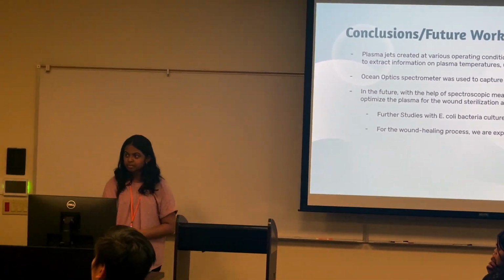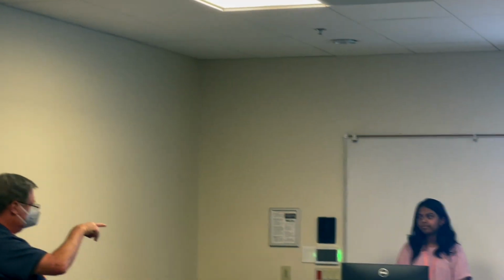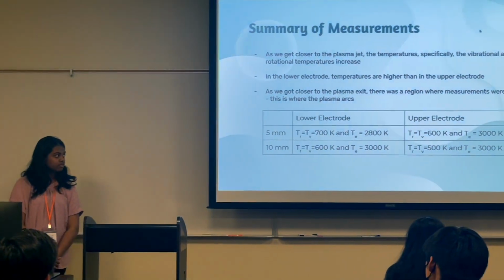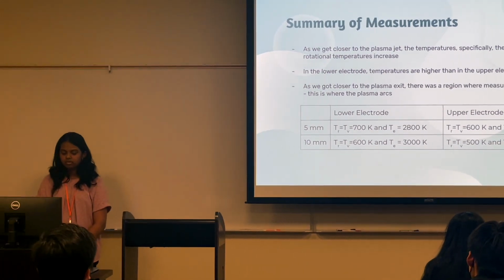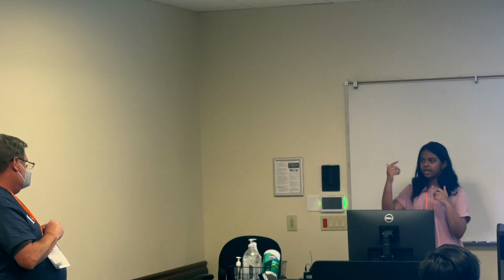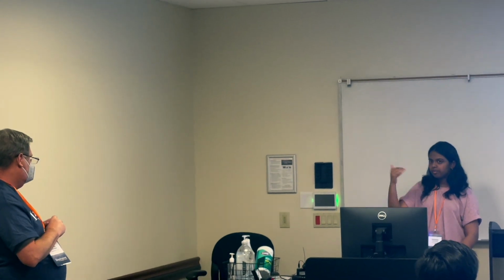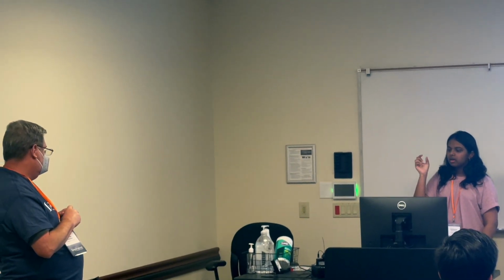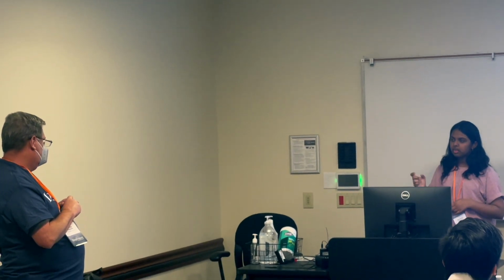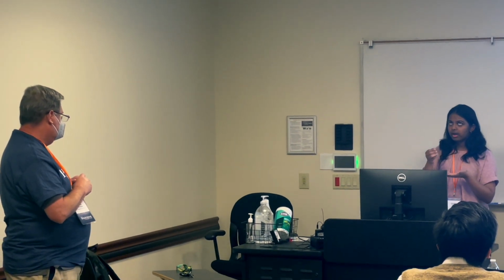If you go to your last table, I think, where you should be at this one. So I was just trying to say, when the distance gets longer, the lower electrode temperature is lower, but the upper electrode is higher. No, in general, when the distance from the plasma jet exit is longer, so we did it in increments of 5, so 5, 10, all the way to 35 millimeters. As we go from 5 to 35 in both electrodes, the temperatures will decrease. But as you go from the upper electrode to the lower electrode, since the lower electrode is closer to the exit, you'll have a higher temperature once it comes out of the lower electrode.